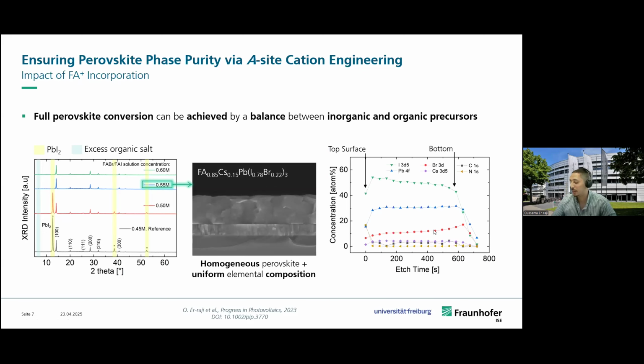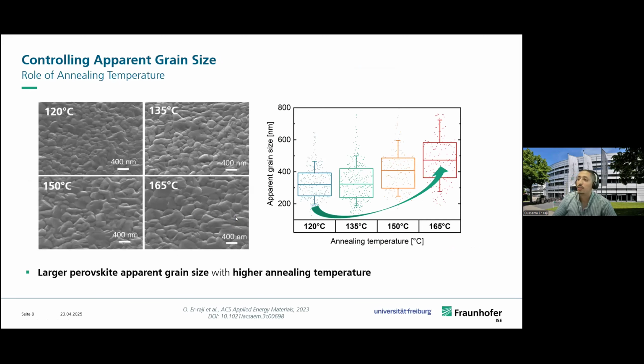Now we solved one issue, but we also observed another issue, which is the fact that we have a lot of grain boundaries. And this again will have an important contribution on the transport of charge carriers within our absorber. How did we find a solution for this? Well, we observed that in the hybrid method, the annealing temperature can really play a big role on the size or on the large apparent grain size formation of the hybrid process perovskite. So here, for example, you can see that by going from 120 degrees up to 165 degrees, we had an increase in apparent grain size.